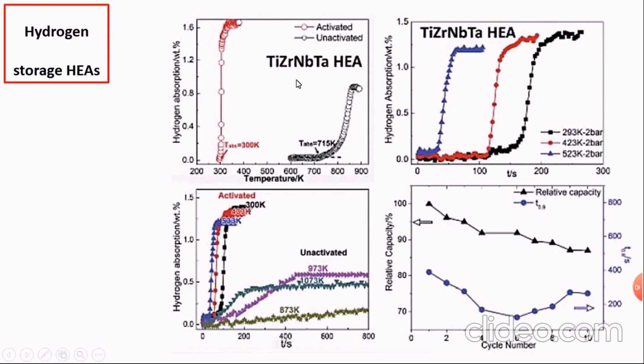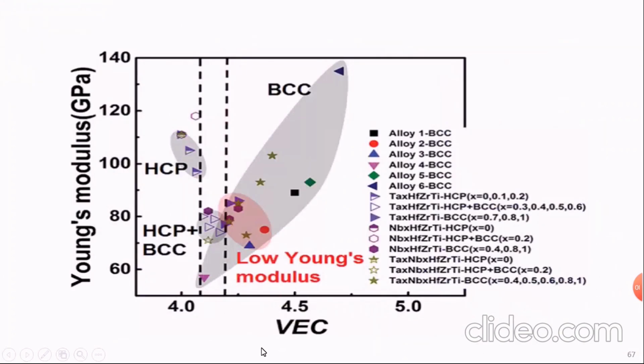in use as hydrogen storage materials. If you see here the comparison between the hydrogen absorption and temperature for different high entropy alloys, you can observe how efficient these alloys are to be used as hydrogen storage materials. Also for biomedical applications, the problem with titanium alloys as biomaterials is their high elastic modulus. Here in high entropy alloys, by controlling the valence electron, we can have a low Young's modulus, which is close to that of the bone. And we have groups of high entropy alloys from which we can choose. So we can choose the alloy which is suitable, for example, for implantation in the body. So it's very good in this application actually.